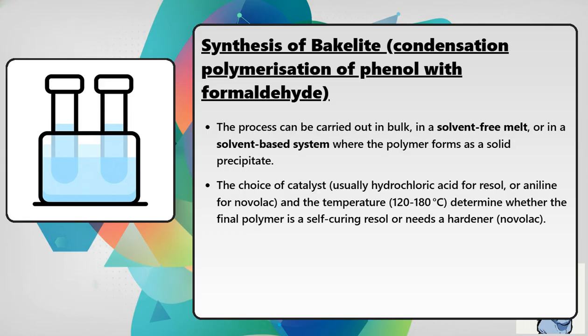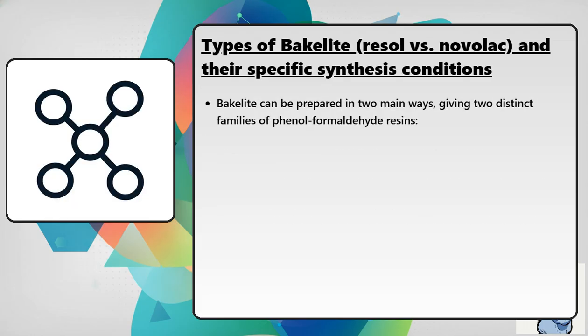The choice of catalyst, usually hydrochloric acid for Resol or aniline for Novolac, and the temperature, 120 to 180 degrees Celsius, determine whether the final polymer is a self-curing Resol or needs a hardener, Novolac. Bakelite can be prepared in 2 main ways, giving 2 distinct families of phenol formaldehyde resins.